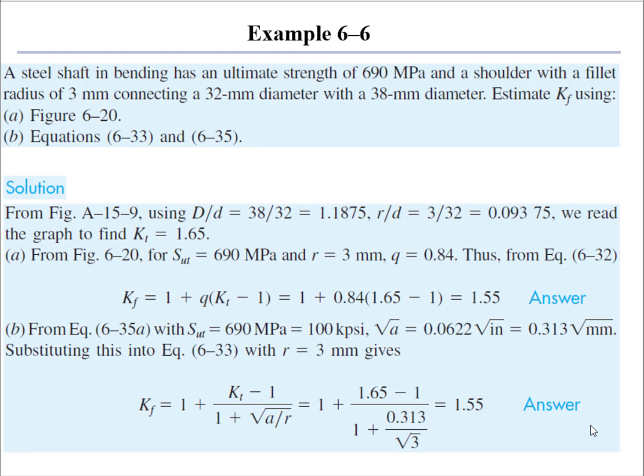The last calculation that I did on my spreadsheet came from example 6.6, which showed the steel shaft in bending with an ultimate strength of 690 MPa, a 3 millimeter notch root radius, and an elastic stress concentration factor of 1.65. It gives me a fatigue stress concentration factor of 1.55 when I calculate a Neuber length scale of 0.313 and convert my ultimate tensile strength, which was 690 MPa, to 100 kpsi. That's everything I did on the worksheet, and so it's pretty easy to solve these problems once you build an Excel spreadsheet to do it for you.